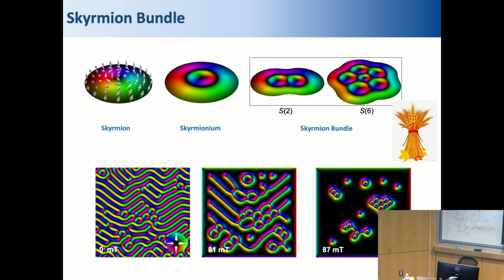We did this numerical simulation. What we did is we first applied a magnetic field in the minus z direction. Under this magnetic field, there is some skyrmion formation, and the center of a skyrmion, as I said, is pointing opposite to the external magnetic field. So the center of the skyrmion is pointing up. Then we gradually turn off the field, and most of the skyrmions are gone, and they're replaced by helical lanes, because helix is more stable at low field, zero field.